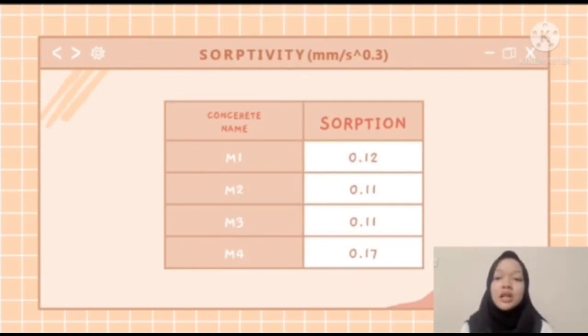The specimen was allowed to cool to room temperature as indicated in the water absorption section. The cubes were placed in the water after the cooling process, ensuring that only the bottom surface of the specimen came into touch with the water. The weight gain of the specimens at regular intervals was used to measure the moisture rise in the cubes. The weight gain of the specimen per unit area of the concrete surface and the square root of the time for the suction periods were then used to compute the concrete